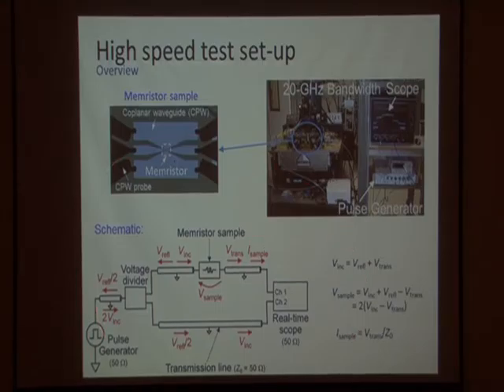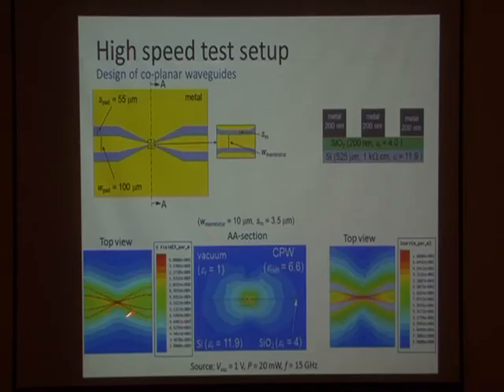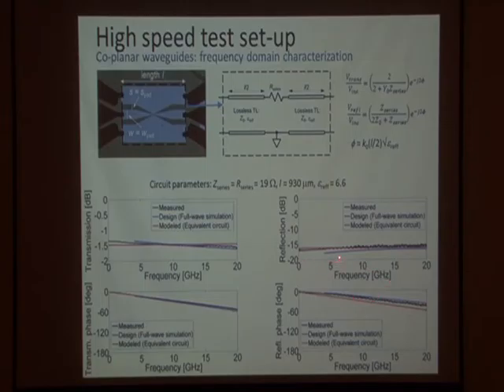So we created this algorithm, and here are the calculations that he did. He made sure that everything is impedance matched, and this is the full wave calculation, and then he was able to show the current going through it. So you see the level of professionalism that Antonio has. He measured, he designed, and he modeled. And model means that he has a lumped element description of the system, just in case you want to do a back of the envelope type calculation. So he understands this really, really well.